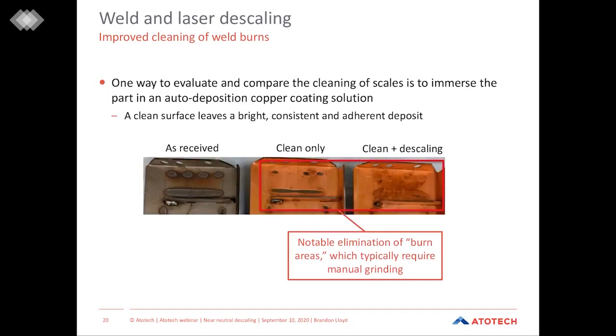So also what we referenced earlier was some of the burn areas or heat affected zones. As you can see here in the image, we show 3 different parts. One is as received. So this is a raw part with no chemical treatment done to it at all. The 2 images on the right will compare a clean only application to a clean and descaling with Uniprep AC. And you can see with the addition of the Uniprep AC for descaling, there's a notable elimination of the burn areas, which would typically require manual grinding to remove and to get good adherence.